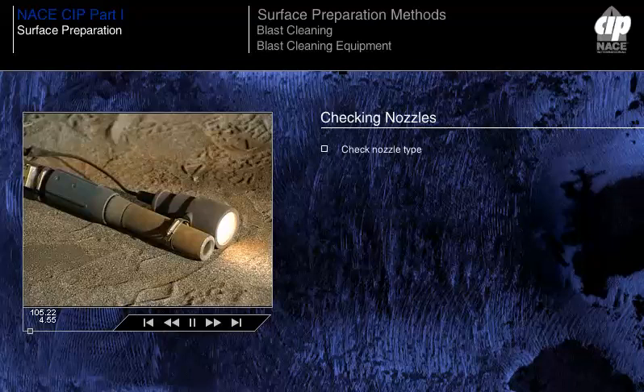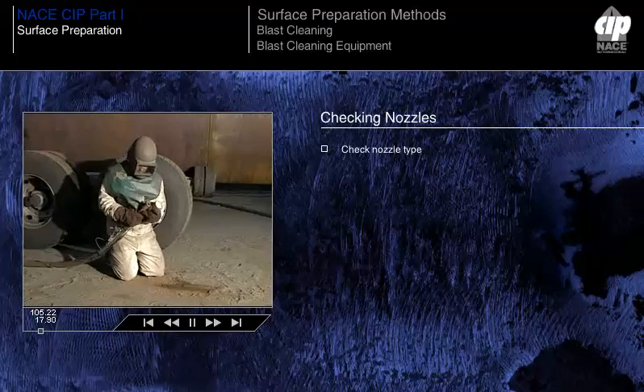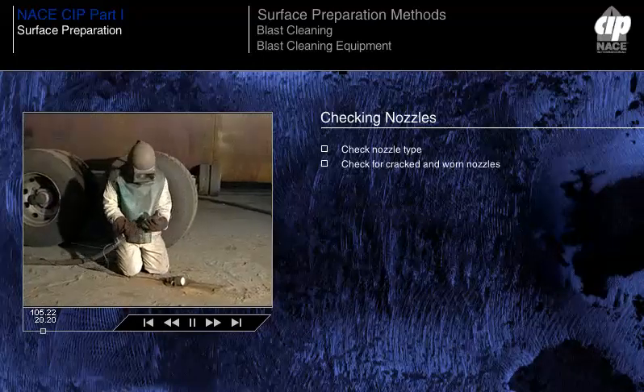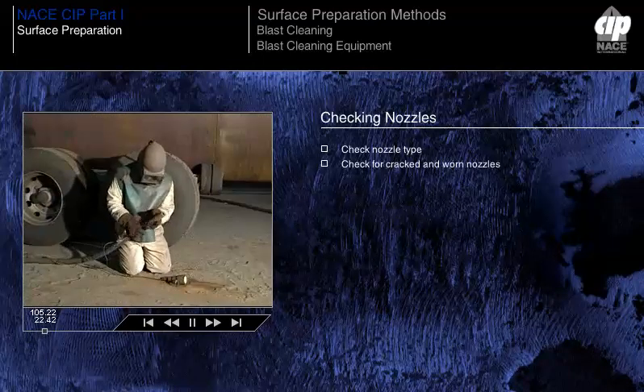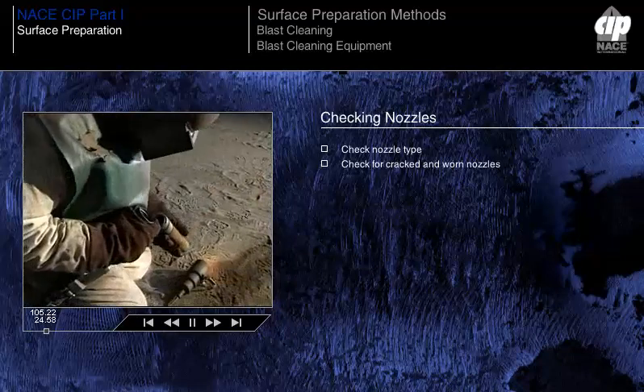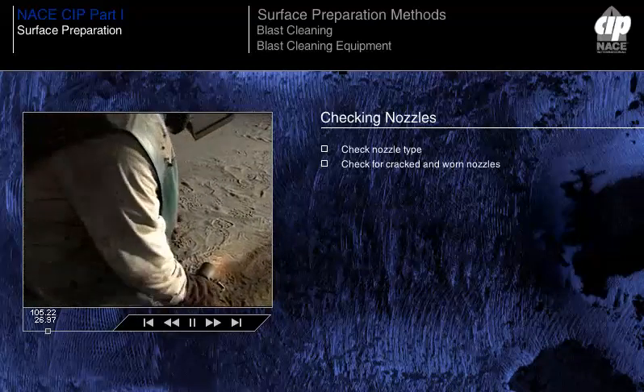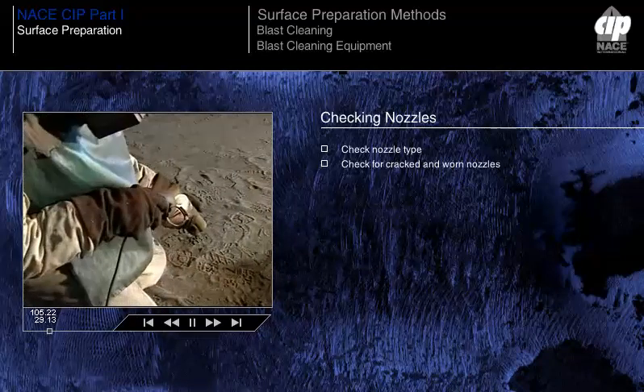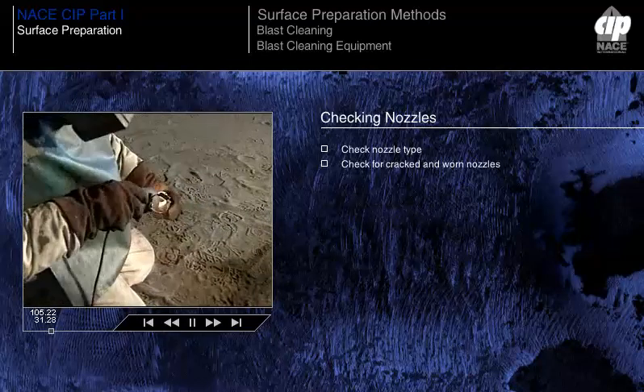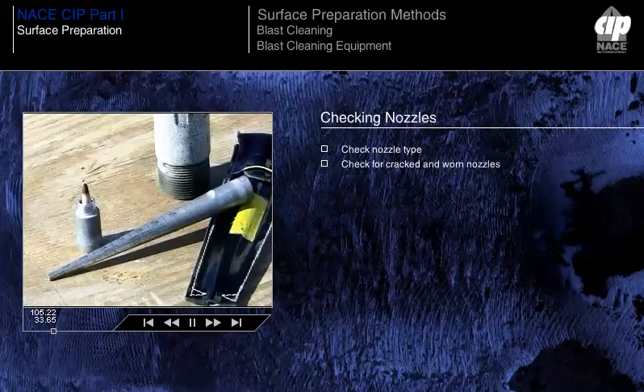Periodically, the user should check nozzle type. The Venturi type provides a higher abrasive velocity than a straight barrel type of the same size. Check for cracked and worn nozzles. A cracked nozzle should not be used because it can create a severe safety hazard. A worn nozzle decreases the effectiveness of the blasting operation. A nozzle orifice gauge is used to measure wear.